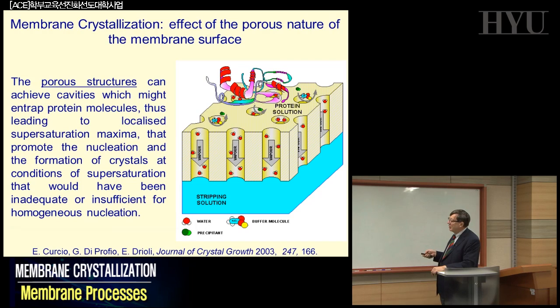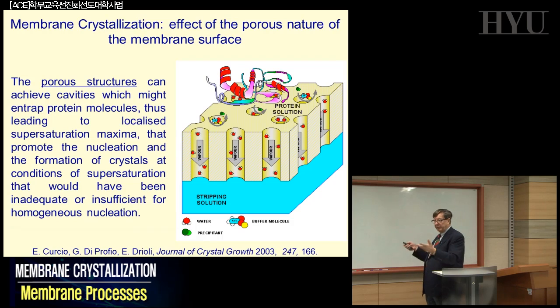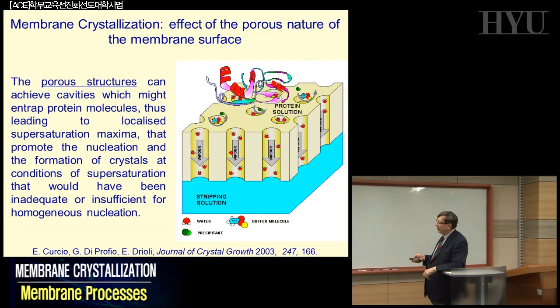That's one of the expectations that you had. The porous structure, that means the porosity on the membrane surface, which means some kind of cavity and a certain level of roughness. Maybe this porosity can entrap protein molecules, leading to localized supersaturation maxima, a very high level of concentration, very localized just at the mouths of the pores on the membrane surface, that promote the nucleation and the formation of crystals at conditions of supersaturation that would have been inadequate or insufficient for homogeneous crystallization.